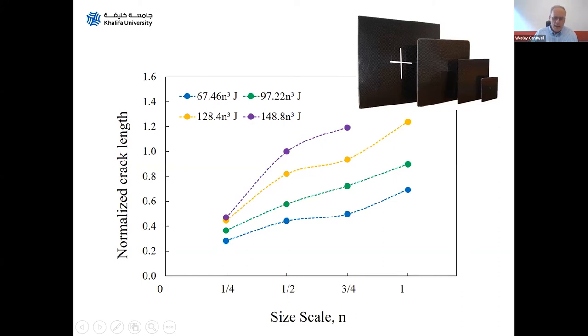And we plot that against our scale size. So here we've got normalized crack length, because the maximum value could be equal to 2, because we could add the warp and weft directions, we've got values above 1. But anyway, what we find is, as we increase our scale size, we get more and more fracture of the fibers. We would hope and expect that these lines might be flat, getting the same response at all scale sizes. But what we find is we get more fiber damage in the larger panels.